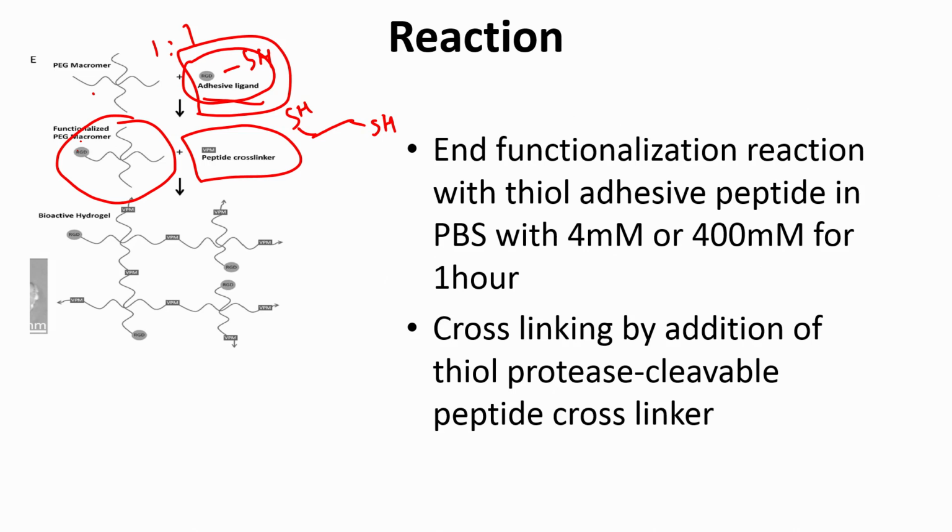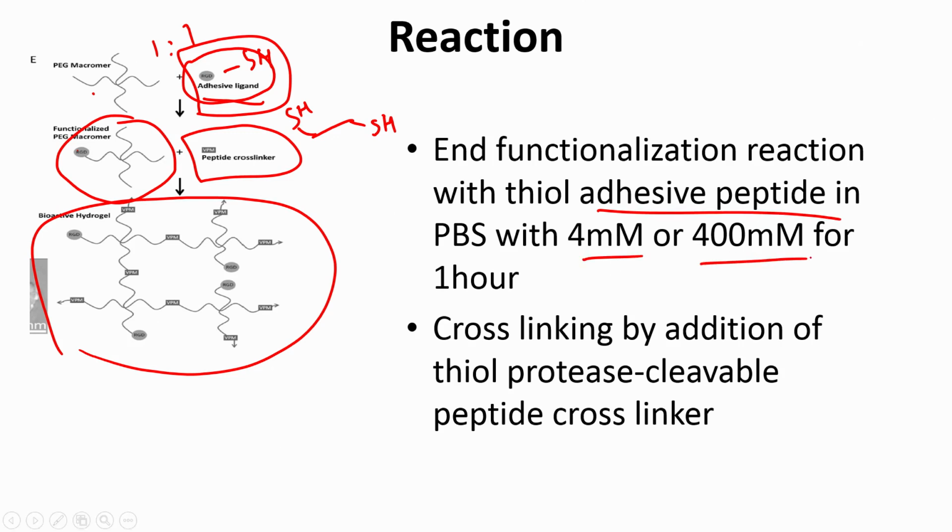So, now it can essentially cross link in a whole network like this. And they have used different conditions. They have used the adhesive peptide at 4 millimolar or 400 millimolar. They have used it for different times up to an hour, and then the cross linking is done by a peptide which is also cleavable, which is a protease cleavable.